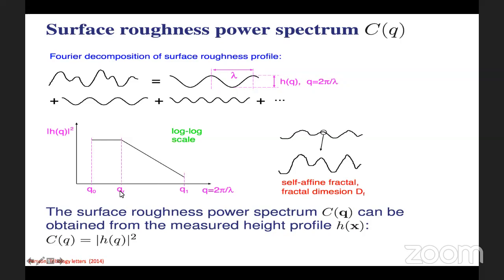The region between q0 and q1 is the most important region. This is where the power law is followed. The slope of this line between q0 and q1 is an indication of fractal dimension. Typically for surfaces, you will have the power spectrum as indicated here, and this straight line, the power law relation, is basically an indication of self-affine fractal surfaces.